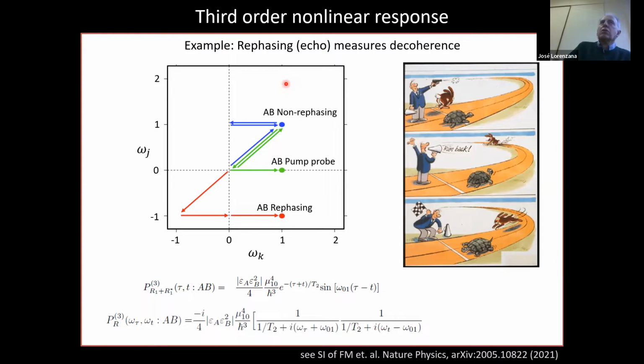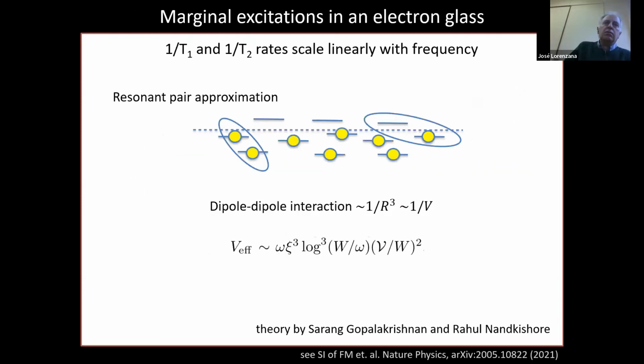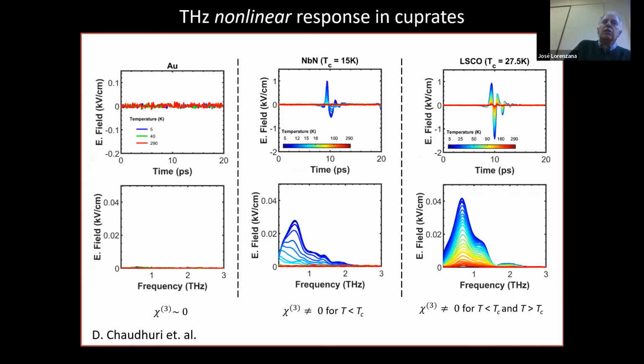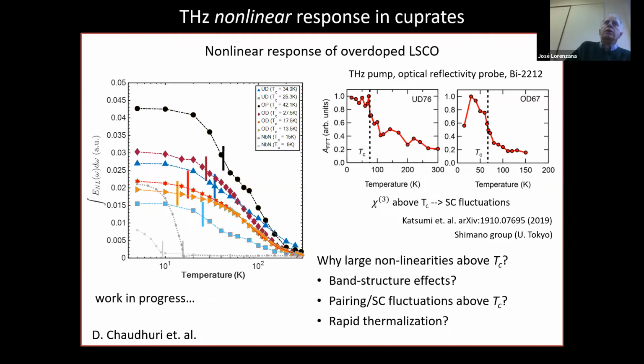Very nice talk. When you show these nonlinear susceptibilities in cuprates, one possibility is that this appears above Tc maybe because the charge density wave has a nonlinear susceptibility. Is it known how this nonlinear susceptibility behaves in charge density waves in general? Right. Actually, we're doing experiments right now on just pure charge density waves, one-dimensional, no superconductivity, and obviously charge density waves are also very nonlinear.